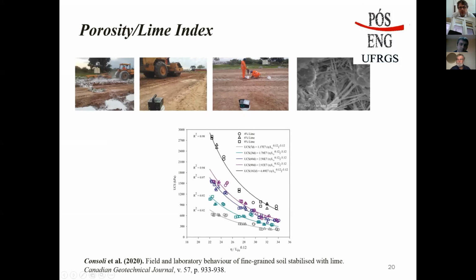And we have shown that this index that we have developed also works for the field. These are results for different time curing conditions, and we have done a longer time condition in the field, and we have collected specimens, and it shows that it's actually the same function, just shifted up from the others here due to the temperature being higher than usual.